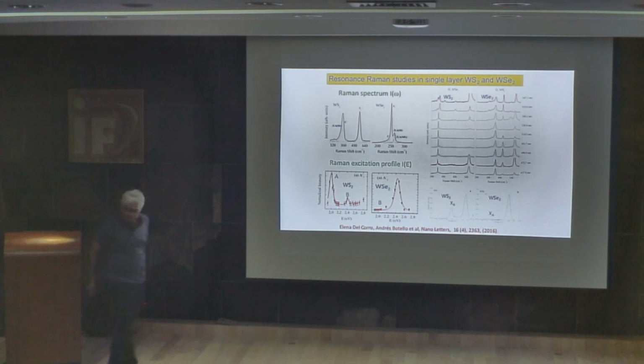And that's where Andres worked with us. It was a calculation that was done. Basically, the idea is that despite the only change being from sulfur to selenium, the electron-phonon interaction changed a lot. It was shown by the calculations of Andres that, for example, in the case of tungsten disulfide, we could see the enhancement of the peak by the A exciton, but in the case of tungsten diselenide, due to the fact that the electron-phonon coupling is not so strong, we could not see the enhancement. Then the theory explained our experimental results.